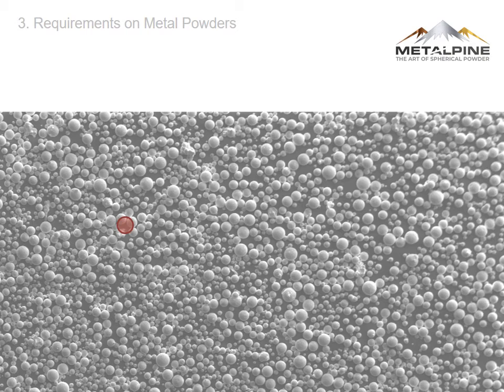And as the size of the laser is not really much bigger than the biggest particles of the powder bed, you would expect that any bad particle, any agglomerate or any other mistake here in the powder bed might probably lead to defects in the printed part.